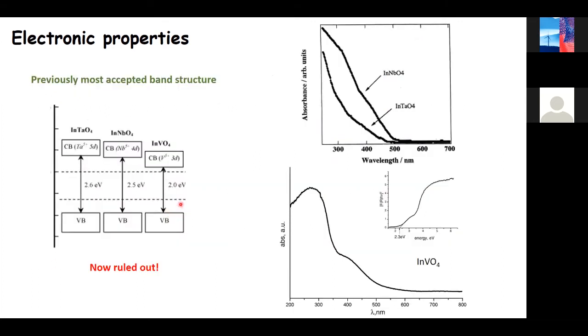So this was the model before we did our study of the band gap. It was assumed that the bottom of the conduction band was mainly due to the electrons of the transition metals, and this gave an explanation to the fact that the expected band gaps were close to 2 eV in the case of the vanadate, and 2.5 in the case of the other compounds. Most of these results come from experiments which were absorption or, in many cases, diffuse reflectance, and people were assigning this to the band gap in these compounds, which is not correct. The band gap is this one,